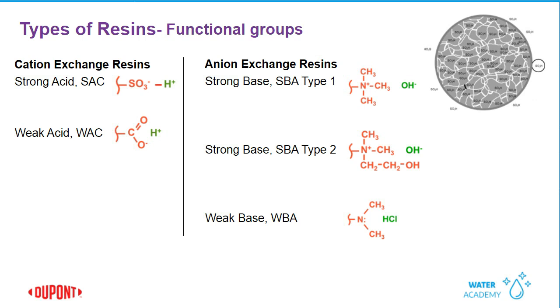Also, the type 2 resin has a temperature sensitivity. So at 35 C, you can't use this above that temperature. So it also limits its use in industrial water. However, if you have a water that's below 35 C, and you don't have a tight silica specification, you might want to investigate using a type 2 strong base anion resin.